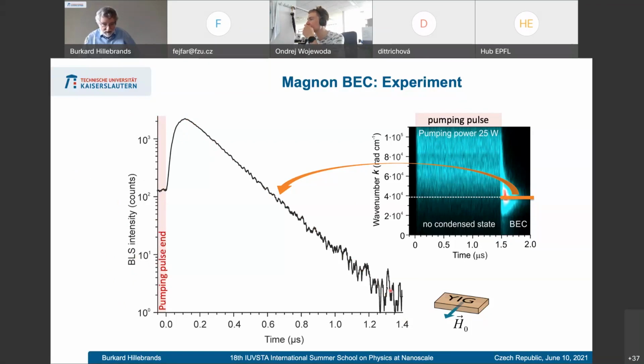And what happens simply here is that these magnons convert to phonons because of the damping, the Landau-Lifshitz damping term, the Gilbert damping, which is very weak, but it is there. But you see, we can operate with these states here over just a microsecond typically. So that works very, very well. So that is a time where we can actually do something useful with it.